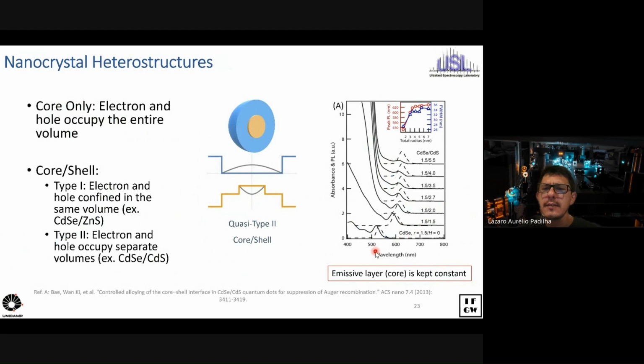So the advantages for this quasi-type 2: we have shown in the past that when you first increase the first few layers of shell, you have some shift in the absorption and the PL, but then you can increase your shell quite a lot, from like 1.5 to 5.5 nanometers, and you barely change your emission wavelength. So the question is, how much does changing the shell change the two-photon absorption? Can you enhance the two-photon absorption by changing the shell? We know that when you go to short wavelengths, where you're in the quasi-continuum spectral range, you increase the linear absorption linearly with the total nanomaterial volume. But how about the two-photon absorption, the nonlinear response?